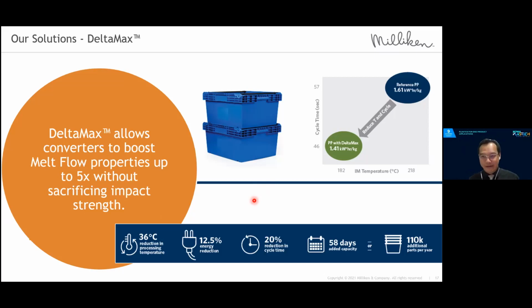I was talking about Delta Max, where by increasing MFR while still maintaining impact strength, you can get some of the benefits of optimizing the injection molding conditions. For example, here, reducing temperature, reducing energy consumption, and therefore reducing the cycle time because you are reducing the melt temperature and the cooling time. And depending on your capacity, you have more days of capacity, and you can make more parts per year with your existing machinery, for example.